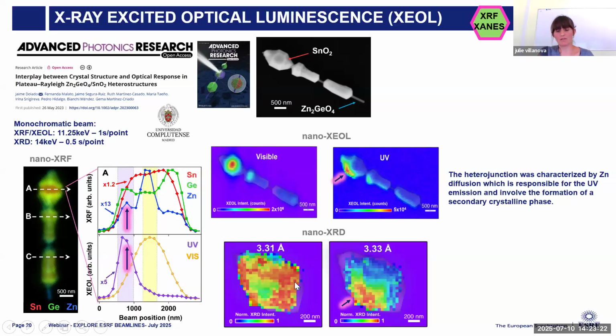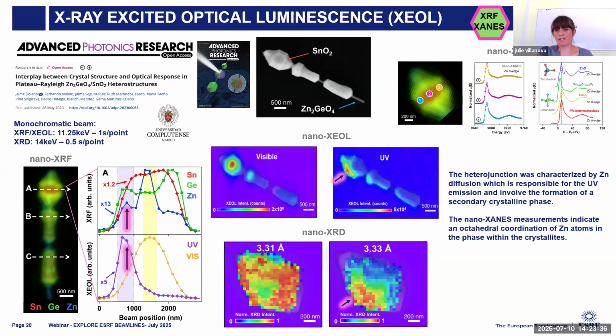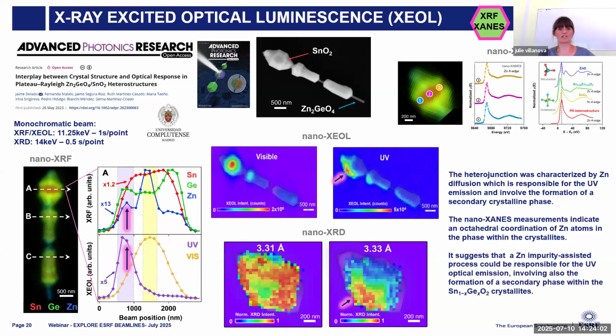And if we look at the diffraction maps, what we see is that exactly where we have the UV emission, we also have a concentration of a secondary crystalline phase. By coupling those measurements with nano-XANES at the K edge of the zinc, the scientists who performed this measurement determined that the nano-XANES indicates octahedral coordination of the zinc atoms in the crystallite phase. So this is a good example that shows how we can combine different techniques to solve one scientific question.